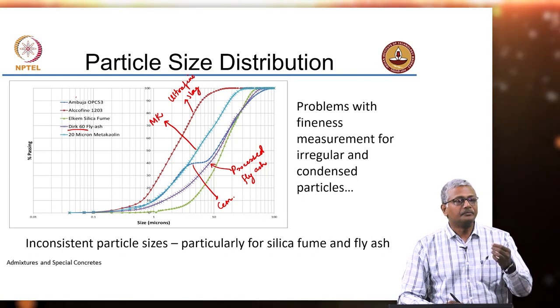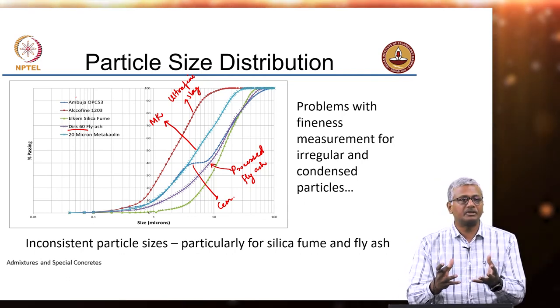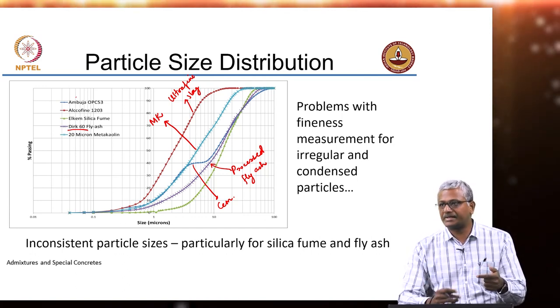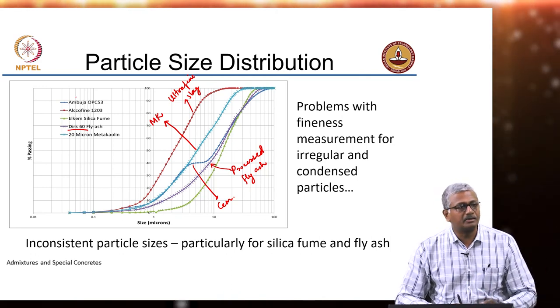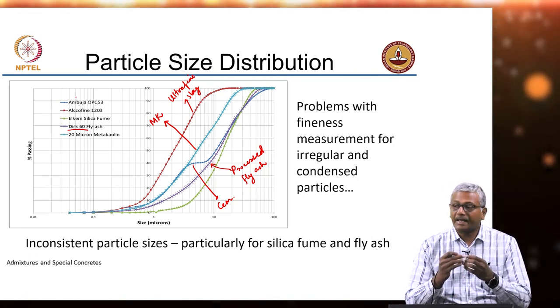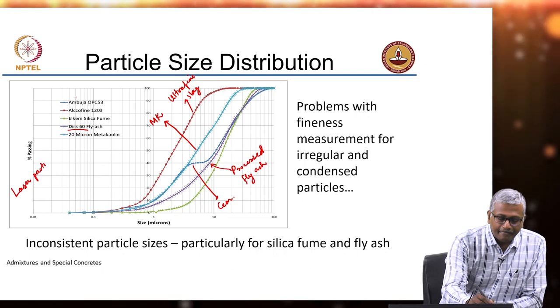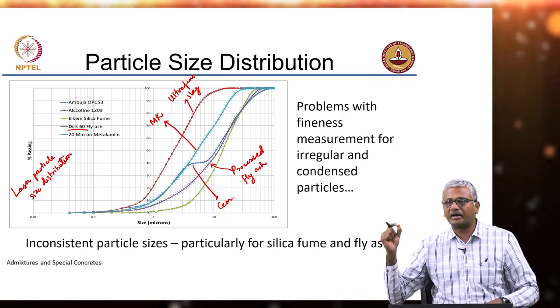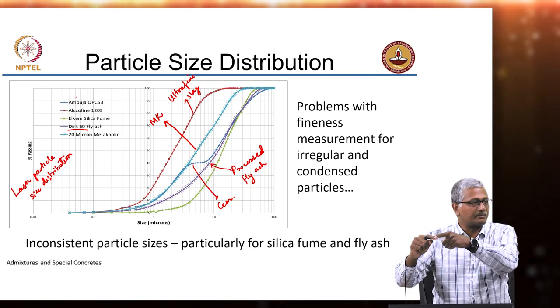You prepare a suspension and then observe the sedimentation by passing light through it. When the system has all particles suspended, light will not be able to pass, but slowly as more particles settle, your light passage will change. We used to call it the Wagner turbidimeter test, but the accuracy is quite limited, so we have to shift to more accurate techniques. The one used for this diagram is laser particle size distribution analysis. As the name implies, we use a laser — a stream of particles at high velocity traveling through air, and a laser strikes onto this stream.